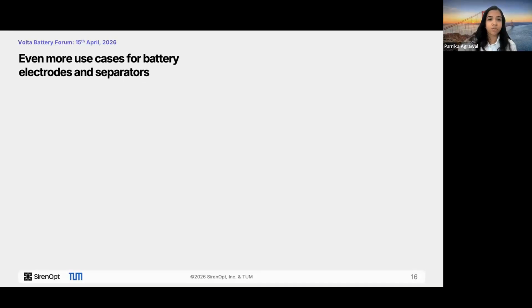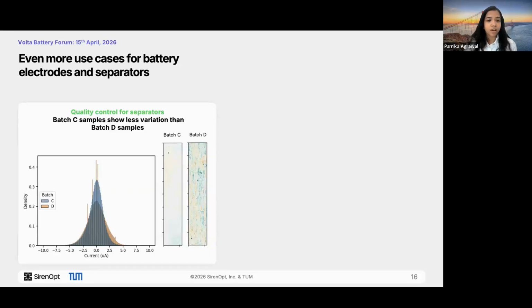Now in this slide, I'm going to show even more use cases for battery electrodes and separators. This first study shows how different batches of separators show a very different degree of variation. The image on the right clearly shows the within-batch variation. This can also be shown in the histograms here, where a tighter distribution is obtained for batch C compared to batch D. This is the kind of intra-sample and inter-sample variation that can be quantified with the data we collect in the physics-based feature space or in the low-dimensional representation space. This does not require any calibration.